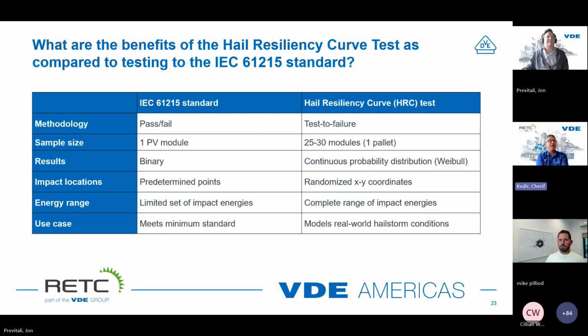So what we do instead, and what we have been doing since the HDT days, and even pre-HDT days, and then now into the HRC time, is we test well within the standard guidelines and beyond the standard guidelines. Our goal is really to try to represent what happens in the field. We perform the test in systematically selected random locations. And what I mean by that is we do random locations, but within certain areas. So for instance, if you just do a random set of locations, you may not have enough locations covering the edge. And so we segment the module, and then within the segments, we have a random location generator that allows us to account for the random nature of hail.